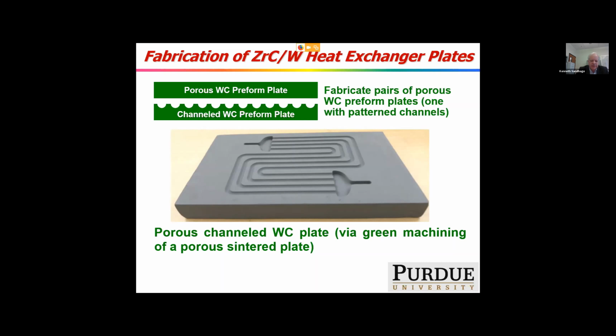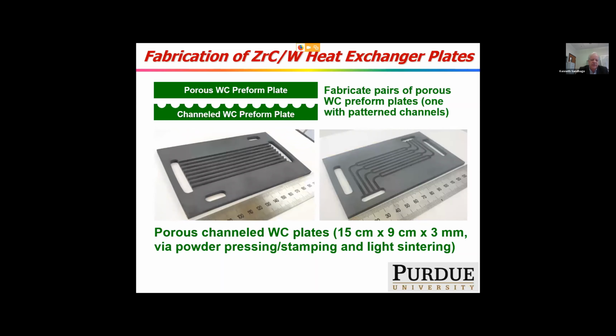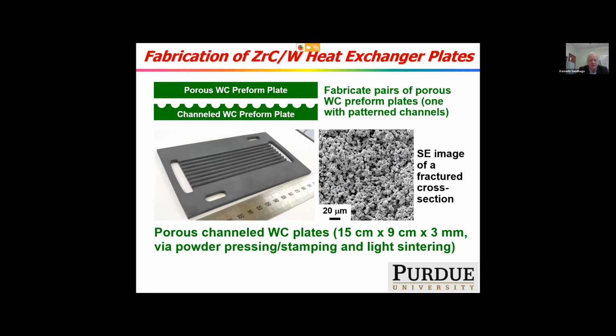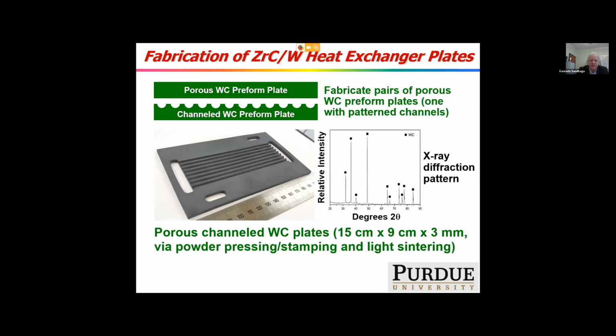However, I think a better way to do this is simply stamping. And so we've made much thinner plates with simple and complicated channel patterns by simply stamping these patterns into the powder, as well as having channel vias for vertical fluid transport as well. If you fracture this, it's made of 5 to 6 micron particle size tungsten carbide, about 50% porous, and it is, of course, WC by X-ray diffraction analysis.